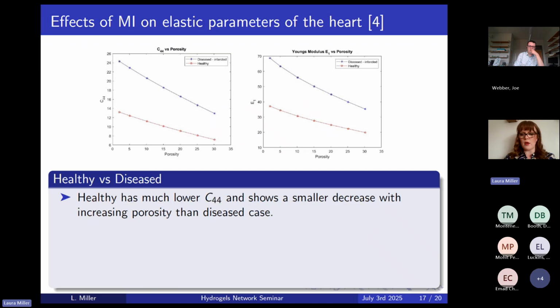Here I have some plots now. I've just again randomly picked a couple of the elastic parameters that we solved in the paper, and we're going to compare those. So I've compared my C44 shear for my diseased case, which is much higher up, and my healthy case here. As we can see, the C44 is a much lower value for the shear in the healthy case, and its decrease with increasing porosity is also much smaller than our disease case. Just to explain the modelling scenario, the reason I was mapping this to an increased porosity was to look at the perfusion of the tissue, so to go from when there's almost no fluid reaching through to when there's far too much fluid reaching the tissue.